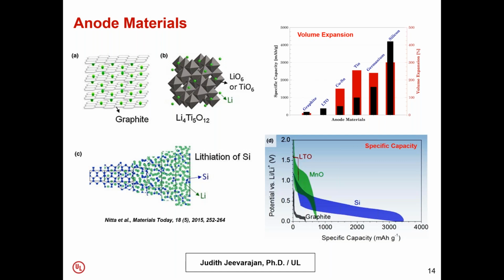Today, a lot of cells have silicon as the anode. When silicon is used by itself, you obviously get a very high specific capacity, but the issue is that silicon expands significantly and also cracks. And what people have done is they have coated silicon with carbon, so the silicon carbon composite has actually helped to reduce the initial irreversible capacity loss. So people are trending towards the use of silicon in the anode.